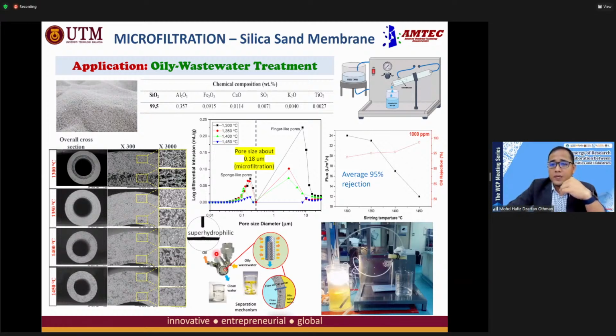We use this technique to do the rejection tests, and we obtained a very high rejection rate with this membrane, 95%. Meaning that if we have 1,000 ppm of oily wastewater, we can reject 95% of it.